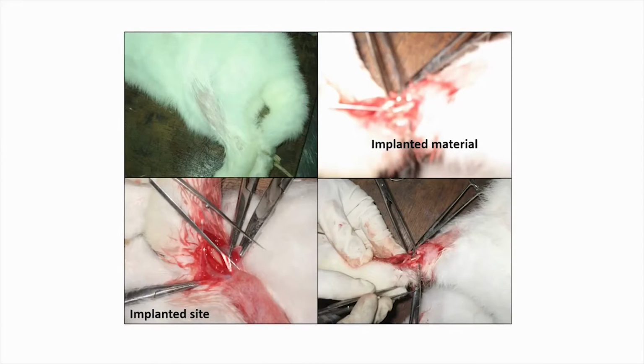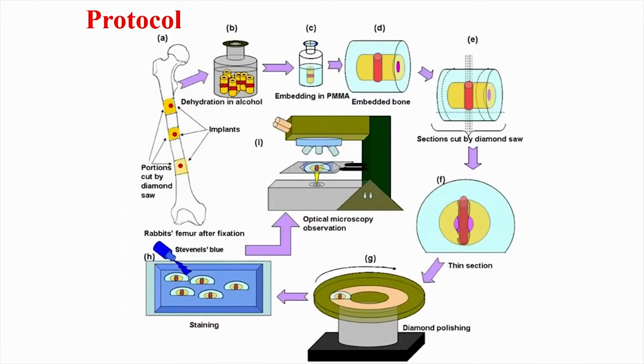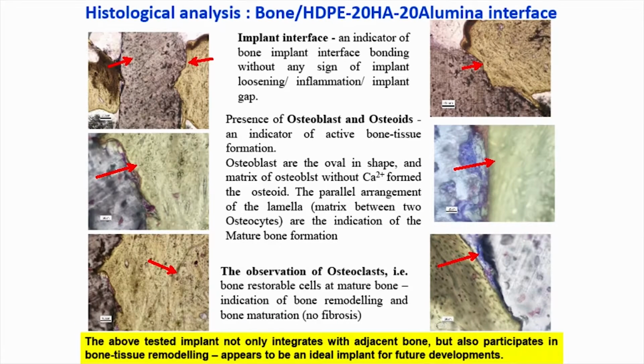Okay, so we have also done in vivo experiments. This is the rabbit model experiment. You can put this implanted material in the femur of the rabbit, and then we can do histological experiments. These experiments were conducted at the All India Institute of Medical Sciences. After that, looking at osteoblasts and osteoids on the implant surfaces, you can very clearly see how these osteoblast cells are active at the bone material interface. So this is your natural bone, and this is your hydroxyapatite, HAP and alumina composite. In this particular case, we observe that high density polyethylene, HAP and alumina are all biocompatible in both in vitro and in vivo experiments.